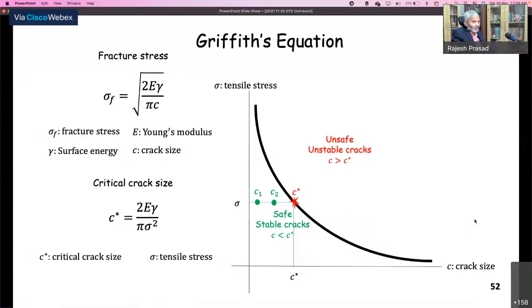And note that it was 1921. The Titanic disaster took place in 1912. So in Titanic time, this understanding of fracture and cracks was just not there. The science had not developed. So nobody worried about how the steel would fracture under what stresses and in the presence of what cracks. You can't make a ship hull without cracks. But the ship will survive if the crack is less than C star, and will not survive if the crack is larger than C star.